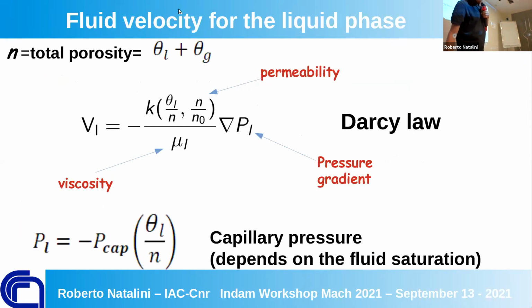And so, how do you find the fluid velocity? The total porosity is given by, by definition, just the sum of the fraction of the liquid and the fraction of the gas. Because otherwise there is the porous matrix. And again, you assume the Darcy law. So you have the pressure gradient, the permeability, and the viscosity of water, which is known.